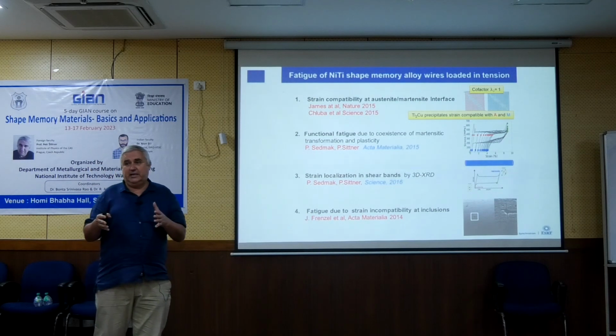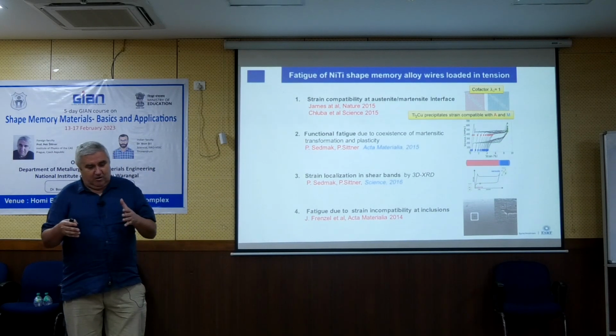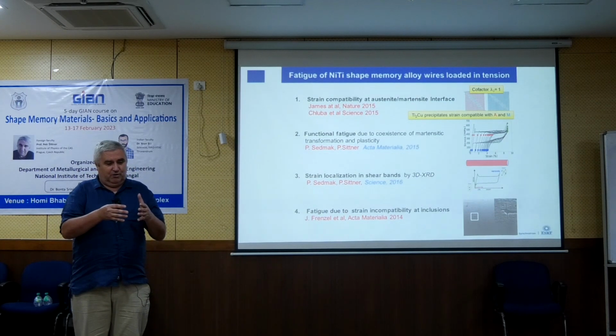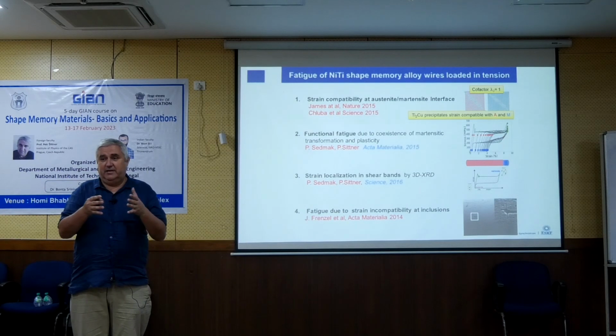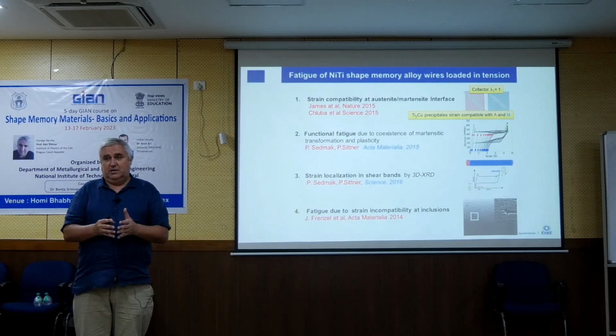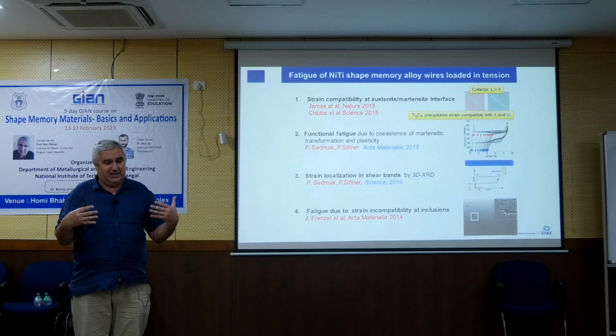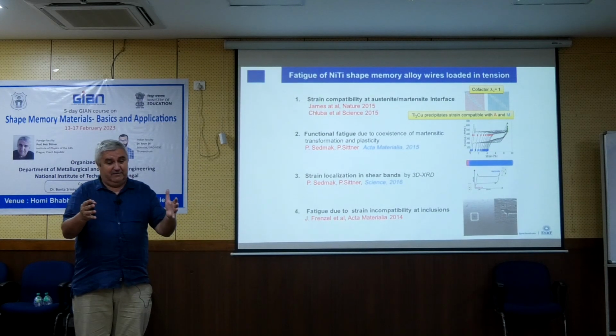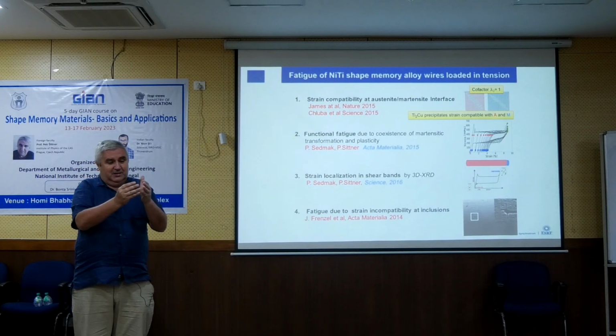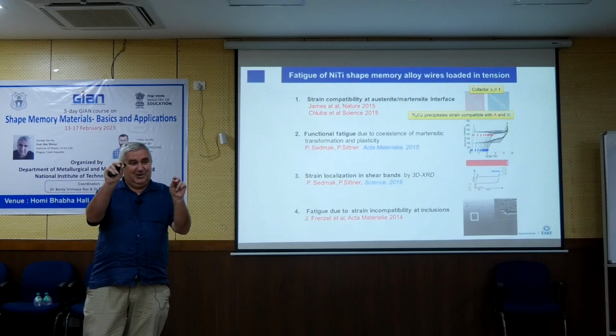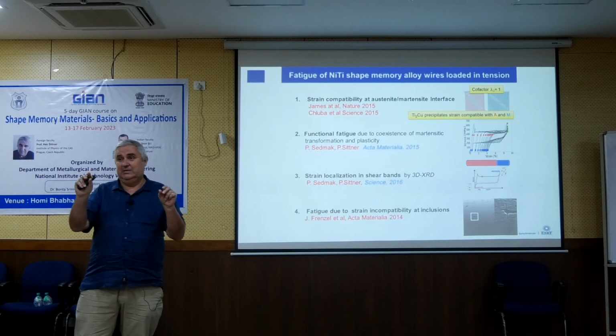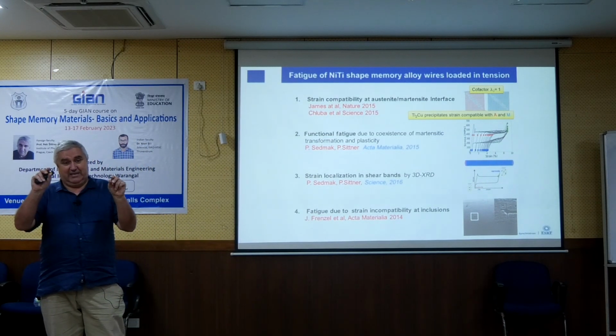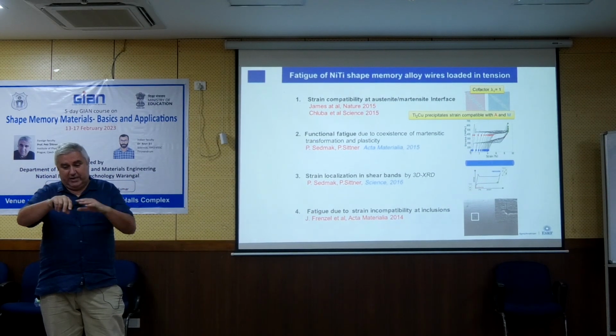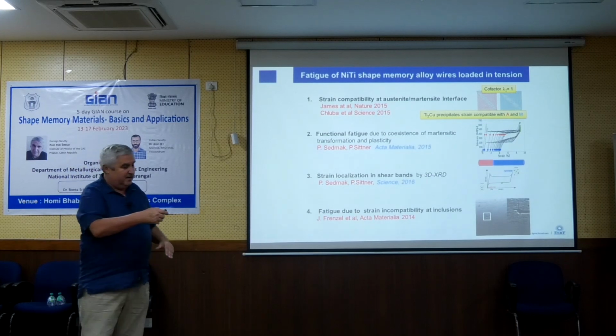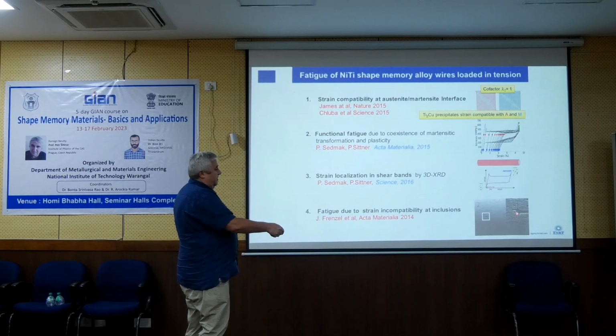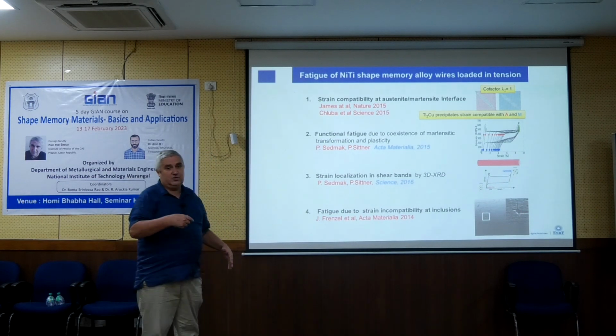We talked the day before yesterday about the presence of carbides and oxides in nitinol, which is cast in big ingots. And so you always have carbon and oxygen coming into the material. Then when it is annealed at high temperature, the carbon and oxide stick together and create particles. The particles are quite big. And then when people look at the surface where the cracks are initiated, they are always initiated at the holes at the surface from which these carbides and oxides are gone.